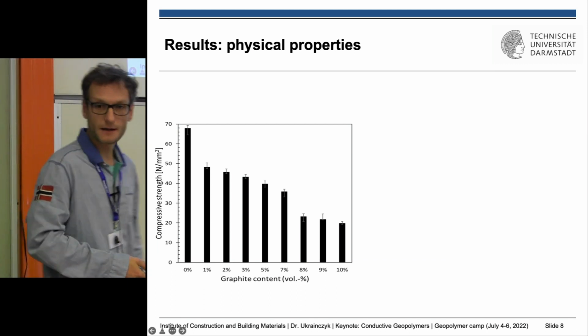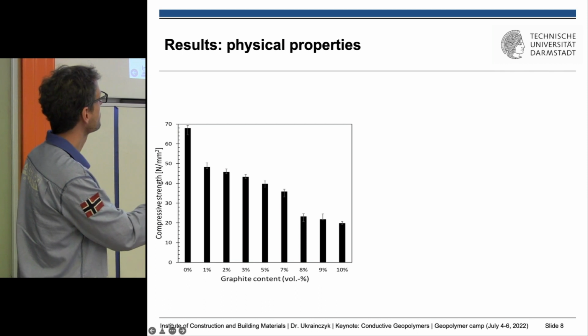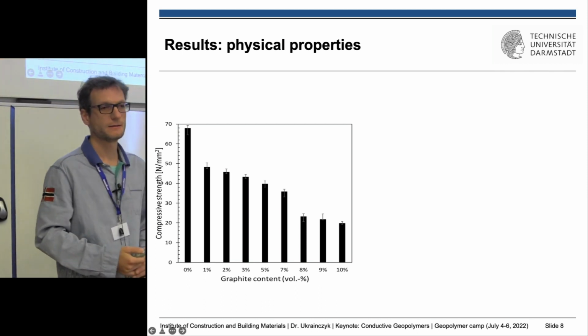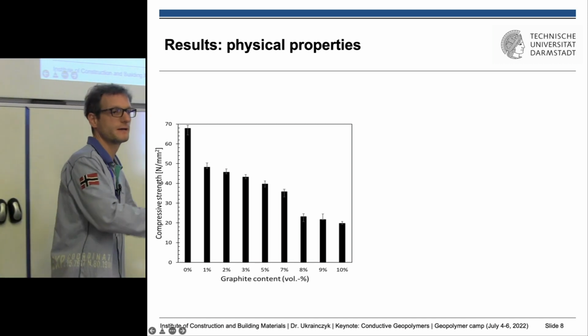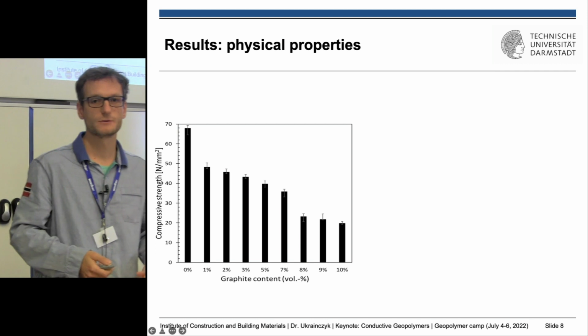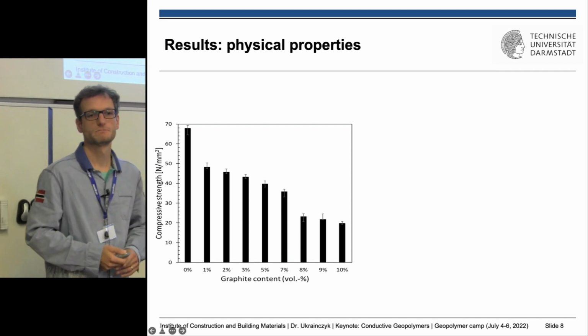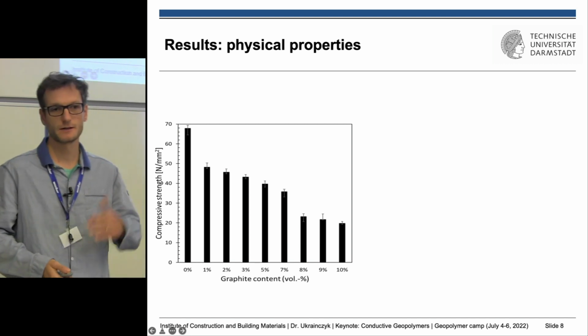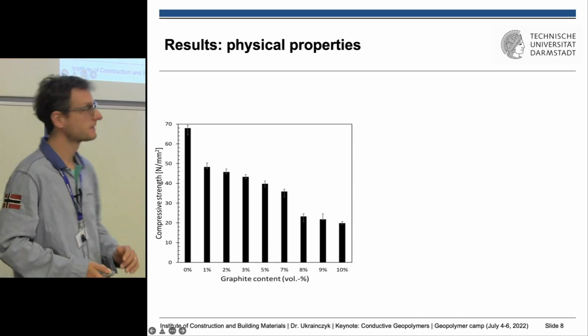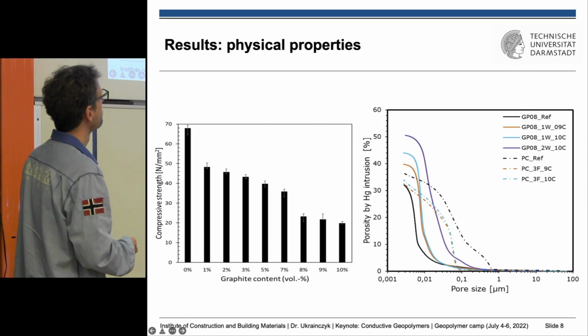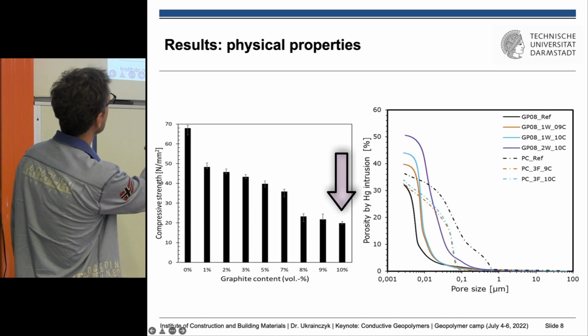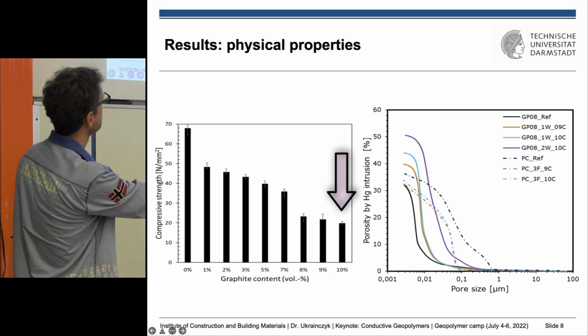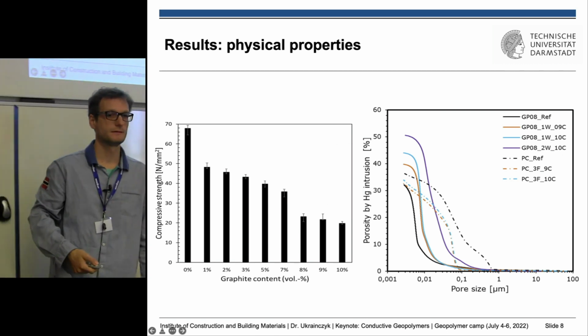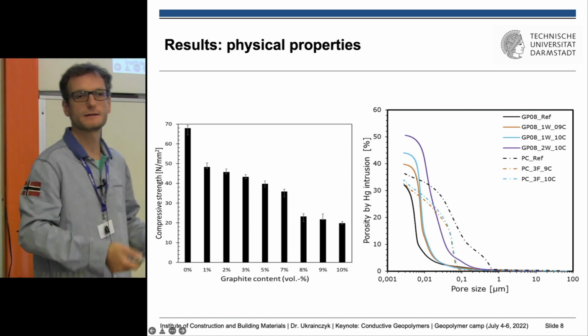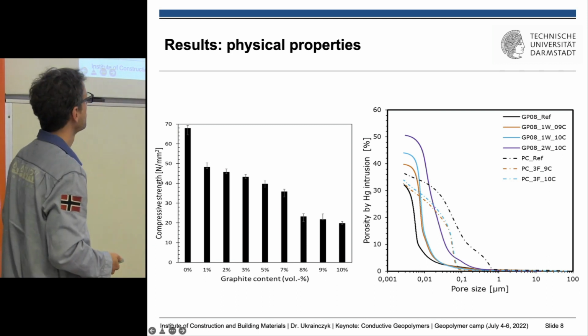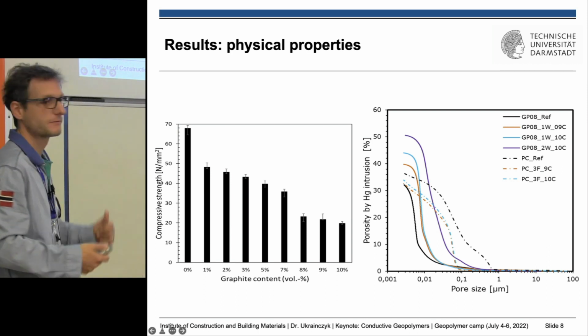So now we can see the compressive strength results. Of course, the graphite reduces the strength. It has a very high surface area, and we mixed it. Actually, it should be mixed with water before adding because we don't want too much water glass to go in. Water glass should be available for the reaction with metakaolin. So I would recommend to pre-saturate the graphite maybe with water. And we can see that for 10%, the strength was up to maybe 15 megapascals, which is still, there is an optimum. How much? Because the electrical conductivity here is important. And of course, the strength will go down. So we are finding some kind of optimum.